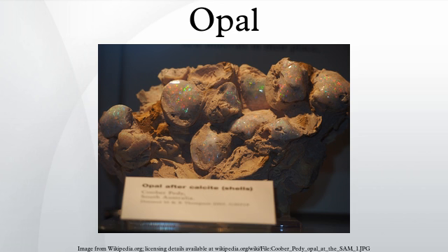Microcrystalline opal. Opal CT has been interpreted as consisting of clusters of stacking of cristobalite and tridymite over very short length scales. The spheres of opal in opal CT are themselves made up of tiny microcrystalline blades of cristobalite and tridymite. Opal CT has occasionally been further subdivided in the literature. Water content may be as high as 10 wt%. Lussatite is a synonym. Opal C, also called lussatine, is interpreted as consisting of localized order of cristobalite with a lot of stacking disorder. Typical water content is about 1.5 wt%.